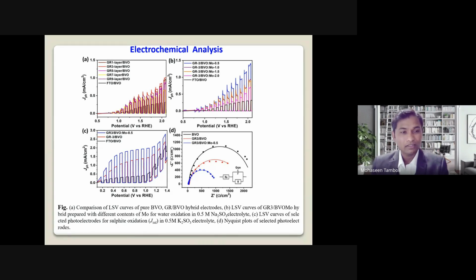Sulfite oxidation is generally favorable for electrical properties because of the SO3H group. But here also, we observed consistent results: after adding graphene and 0.5 molybdenum, it shows the highest photocurrent compared to pure bismuth vanadate and graphene BiVO4. Again, we checked the conductivity of the material by using the Nyquist plot. In the Nyquist plot, you can see the bismuth vanadate, graphene, and molybdenum bismuth vanadate graphene.